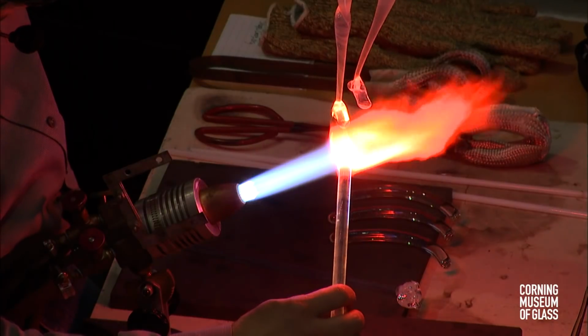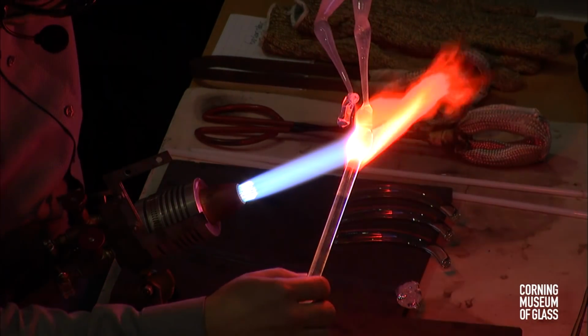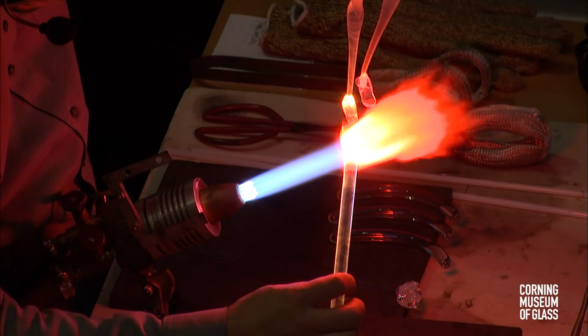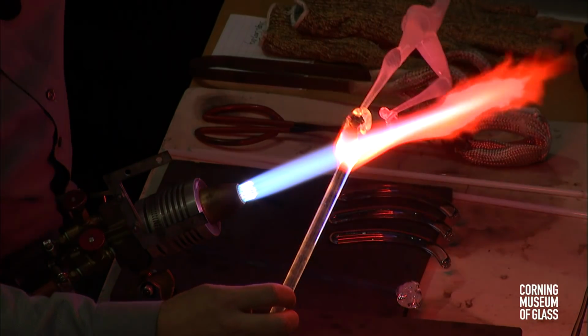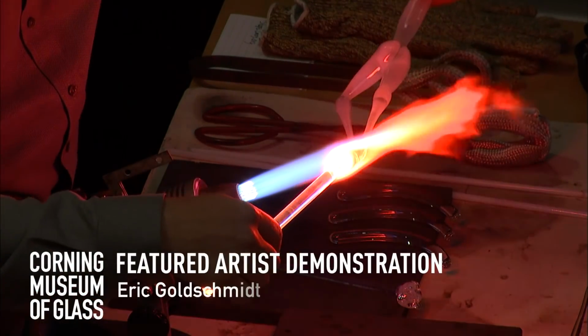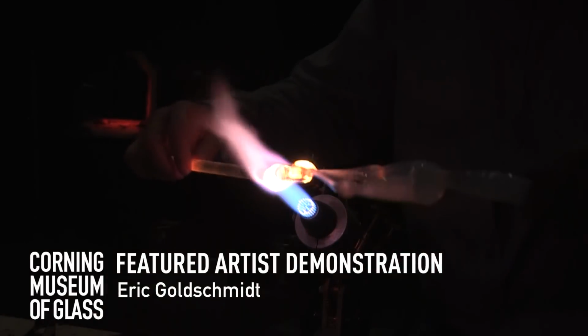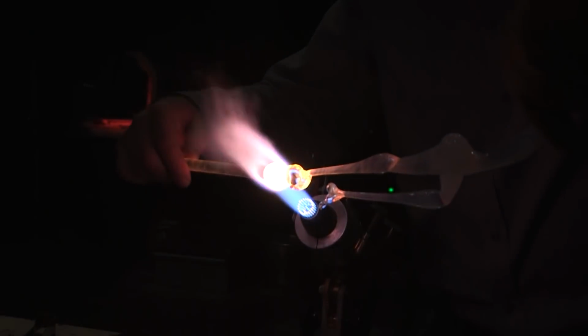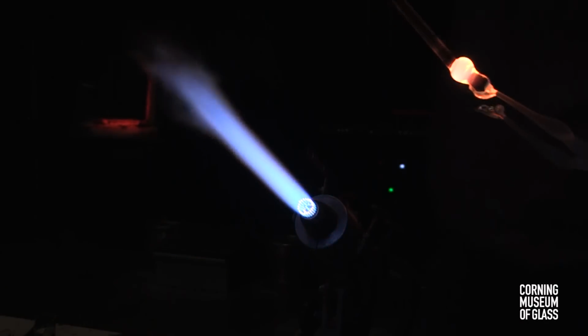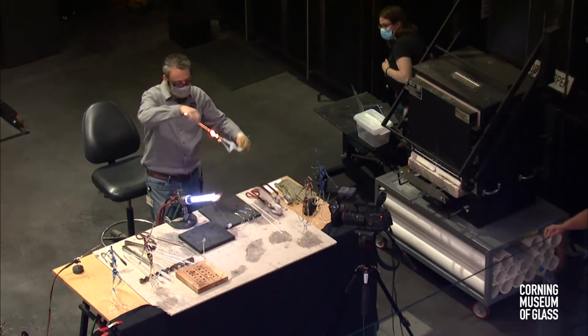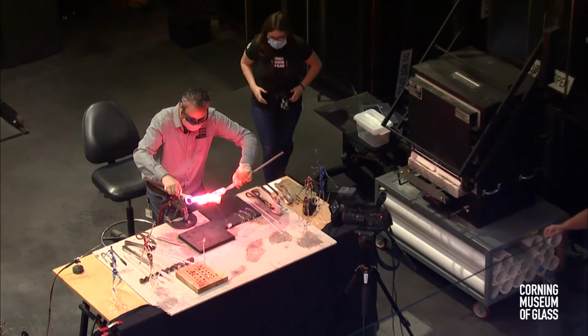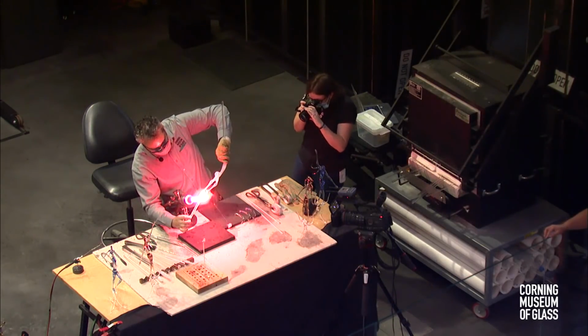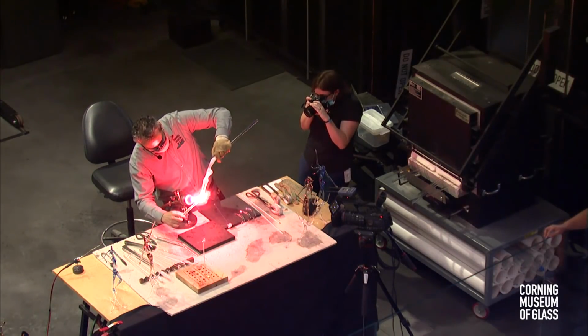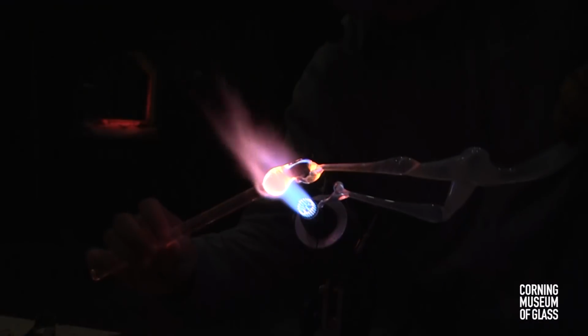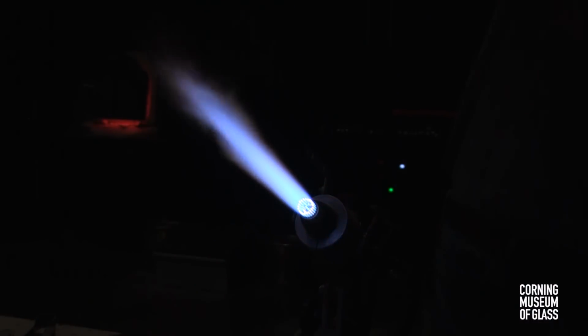I'll bring the oven up from cold and up to 1050 Fahrenheit as fast as the oven will go up. And for a figure this thickness, I'll generally soak it for about 2 hours and then shut the oven off and let it come down as fast as the oven is able to cool down. It's another nice thing about borosilicate. It's much friendlier in the annealing end of things as well, since it tolerates temperature change so well. Annealing schedules tend to be shorter than many other glasses.